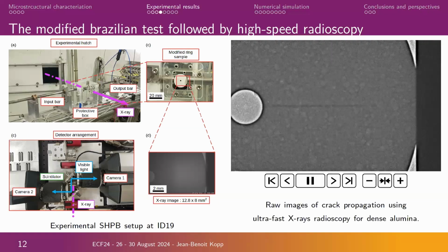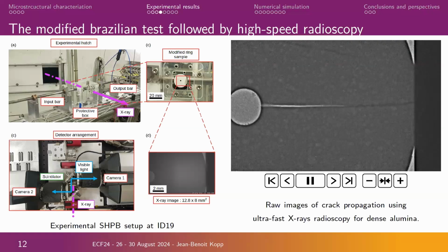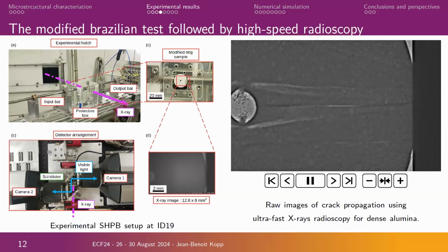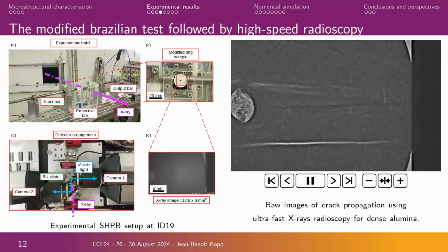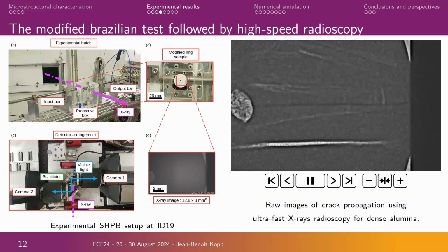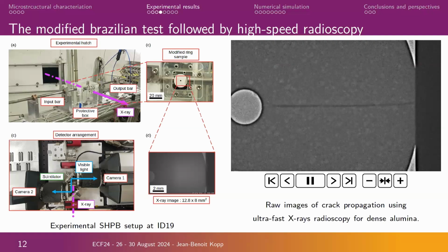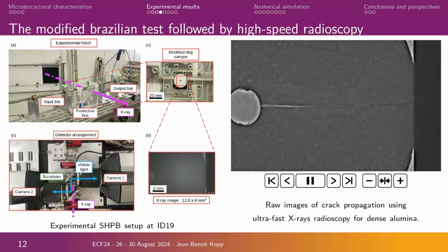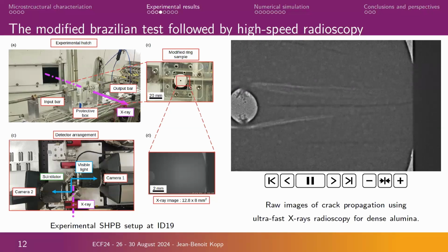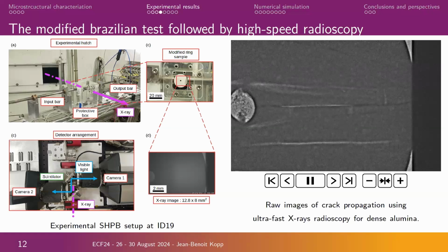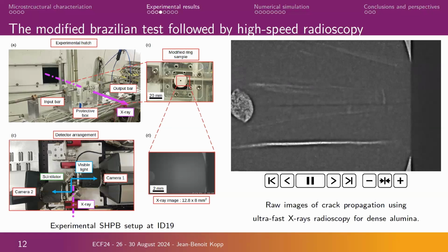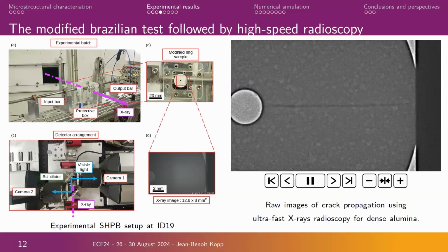So you have an example here with the dense alumina. You can follow the porosity just over there. And what is interesting, I don't know if you follow that, but we have a main first crack just over there in dynamic regime, and after you have the global fragmentation of the specimen. So it was interesting to follow that and to be sure that we can initiate one main crack before the global fragmentation of the specimen.